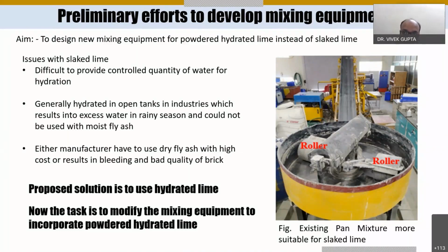When we change our raw material from the slurry to the powdered form, we found that the existing mixer needs improvement, because the roller type pan mixer you are looking at right now in the presentation is especially designed for grinding lime putty. Another reason we selected powdered hydrated lime is that in the industry we generally slake the lime in big tanks. We do not have a controlled provision for the hydration of that lime.